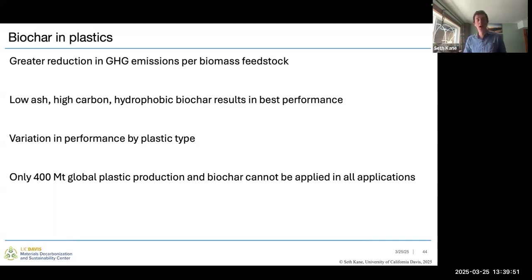When we think about what we want, whereas in our concrete, we wanted high silica content and hydrophilic biochars, here in our plastics, we want low ash content, high carbon content, hydrophobic biochars. So we're not necessarily seeing the exact same resources being the most beneficial in each of these cases. So we might want some more wood-derived high temperature biochars in our plastics, whereas we might want something like rice hull ash in our concrete. Thinking about the availability of these, there's only about 400 million tons of plastic production globally. We can't apply our biochar in all applications. And so we could potentially be replacing some of our petroleum-derived carbon additives in a number of applications with biochar quite easily. And it's been pretty well demonstrated that these have equivalent properties.